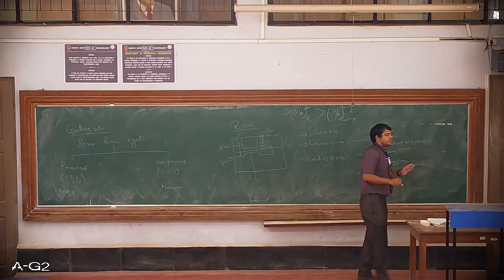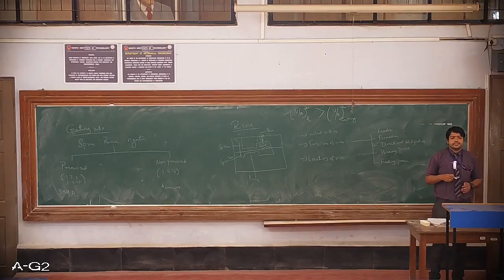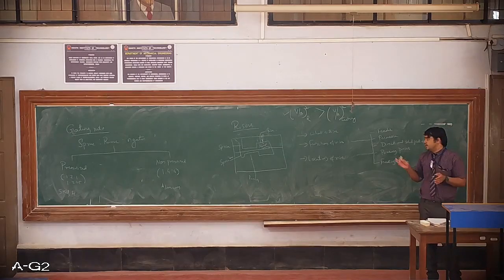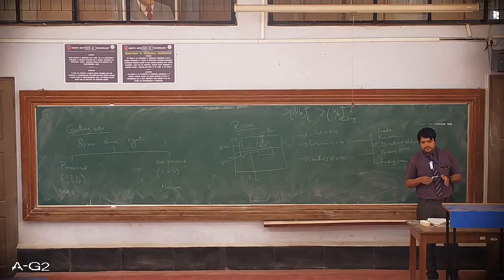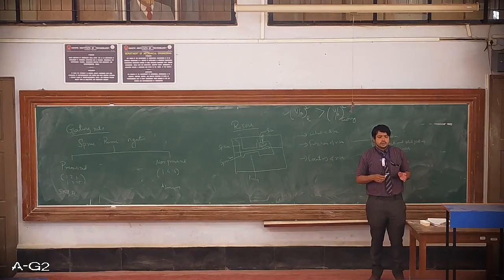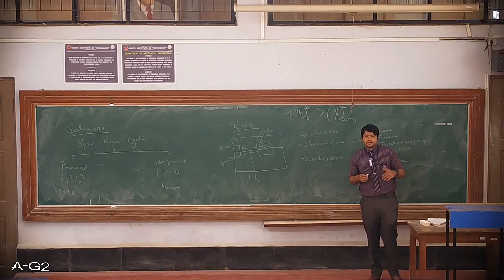Another location of the riser will be the sides of the casting. So in certain cases we require risers which have more dimension as compared to the casting surface, nearly the same or more in some cases, especially in the case of steel. The riser dimensions we get by calculation or practically will be more. The casting yield is also less in the case of steels, whereas in the case of certain metals like grey cast iron, the dimensions we get are slightly less, or the casting yield will be somewhere around 75%. We are going to do certain calculations today on this casting yield.